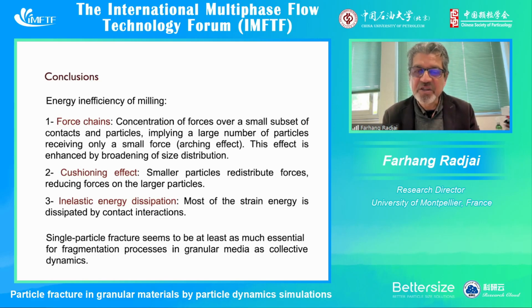The second effect is the cushioning effect, and we showed using modeling that this is important for grinding in ball mills. It's a very important effect for why the milling is not efficient. And the third one is that most of the strain energy is dissipated by contact interaction. So even single particle fracture properties are important for grinding. It's not only because we have force chains, it's also because at lower scale, inside the particle and at the interactions between particles, we have this inelasticity, and most of the energy is actually dissipated in general, even when we have a high restitution coefficient, in interactions between particles.